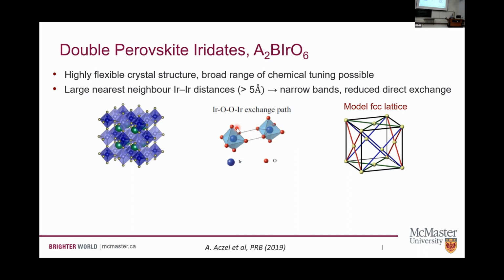It's really flexible. You can grow just a vast range of different materials where you substitute different A site ions, different B site ions, different B prime site ions. And so you get all of this space for chemical tuning. And again, if what we're looking for is big nearest neighbor iridium distances, these are over 5 angstroms, so there shouldn't be much direct overlap between iridium wave functions. So we expect small direct exchange and these narrow electronic bands that might help us get close to this ideal J effective 1/2 picture. So if you put something non-magnetic on the B site here, then you get a network of iridium O6 octahedra that you can map onto a face-centered cubic lattice. So the iridium octahedra is supposed to be the dark blue here, and they can be considered down here. And you get different Kitaev possibilities on your face-centered cubic lattice, shown here in the red, blue, and the green bonds.